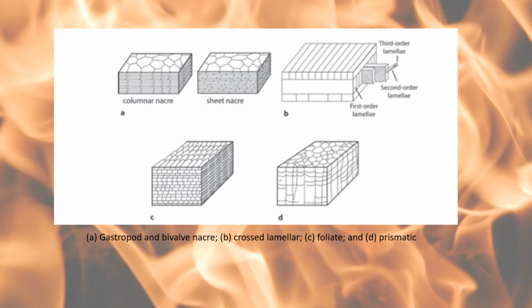The first, nacre, also known as mother of pearl, occurs in two different forms, in gastropods and bivalves. So in gastropods you get columnar nacre, which are these stacked tablets which are glued together in stacks, and then the stacks themselves are glued together. Sheet nacre is characteristic of bivalves, and that tends to be a little bit more lamellar. So as the stacks are building up, the crystals coalesce to form these sheets that lie parallel to the surface of the shell.